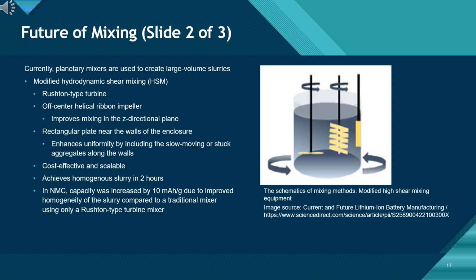A Rushton-type turbine provides strong radial flow, while an off-center helical ribbon impeller enhances axial, Z-direction, mixing. A stationary rectangular plate positioned near the vessel wall helps capture slow-moving regions and break up aggregates that typically accumulate there. This hybrid configuration is both cost-effective and scalable, producing a fully homogeneous slurry in about 2 hours.